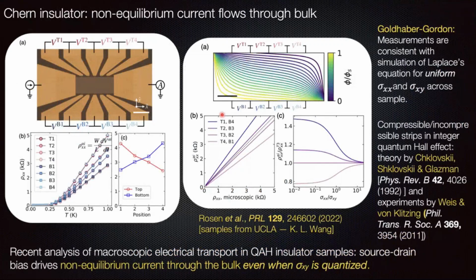Incidentally, at the time that Katya and Matt were showing this data, David Goldhaber-Gordon started talking to us, and they had some data, just purely electrical transport data, that had been sitting around for some years. This is Ilan Rosen's work. And then they realized that they could interpret all of their data with a model that says the current is flowing in the bulk of the sample. And this is just by doing measurements very systematically as a function of different contacts, and then matching it with simulation of Laplace's equation for a uniform sigma XX, right? So current flowing through the bulk.